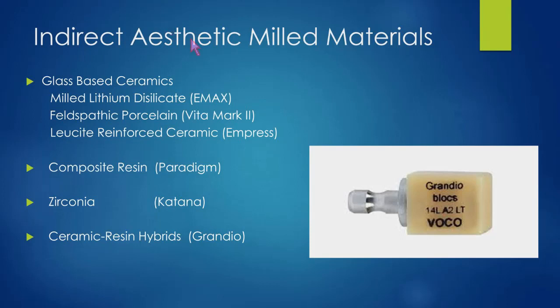So the first category are the glass-based ceramics, and we have in that group milled lithium disilicate, or EMAX, as an example. The feldspathic porcelains like Vita Mark II, one of the first materials we were using for our CEREC, and then certainly the lucite reinforced ceramics like Empress. They're very beautiful materials. They do have a drawback to them in that they can be very prone to fracture, certainly when margins get thin. The thinner these materials are, the higher the requirement that they be bonded. And also, most of these materials will require some other type of secondary heating, meaning if you're making EMAX in the office, you have to put it into crystallization. And even for feldspathic porcelain, a lot of times we're still going to put it back into an oven for glazing after we finish the restoration.